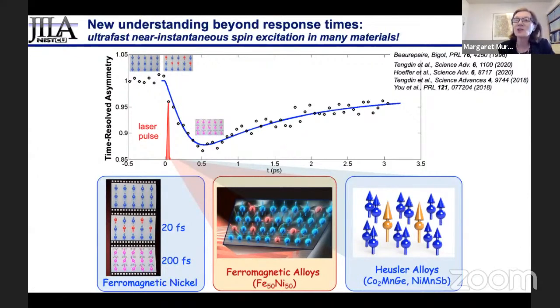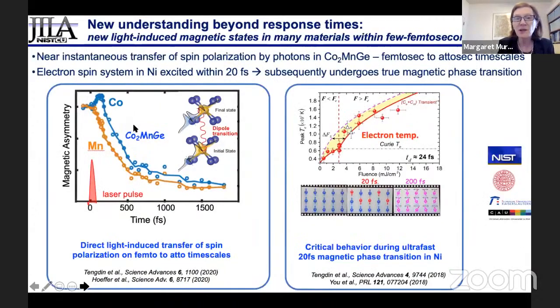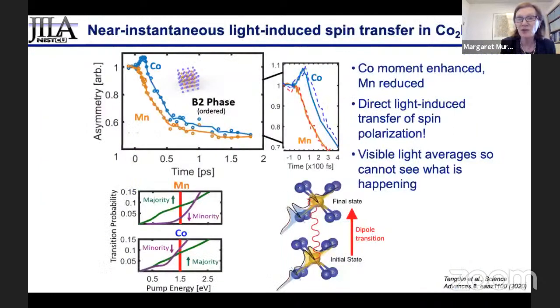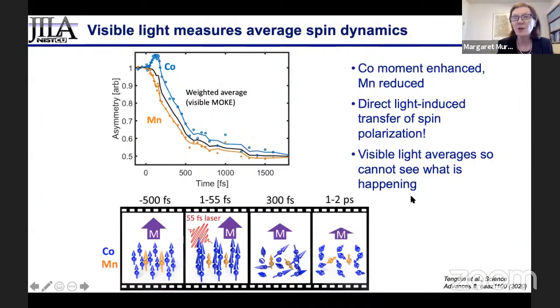But by looking at the instantaneous electron temperature, we could see the energy being transferred to these high energy spin flips. And we've seen this in many magnetic materials, that there's almost instantaneous direct transfer of spin polarization by light, either through these high energy spin flips, which we believe may be mediated by exchange scattering, or by just direct transfer of polarization because of the band structure of the material. And so that's what in these Heusler alloys, we've seen measuring the instantaneous magnetism in two different elements in the alloy. We saw that the magnetic moment increased on one side and decreased on another side, essentially because of the band structure. So it's direct light-induced transfer of spin polarization.